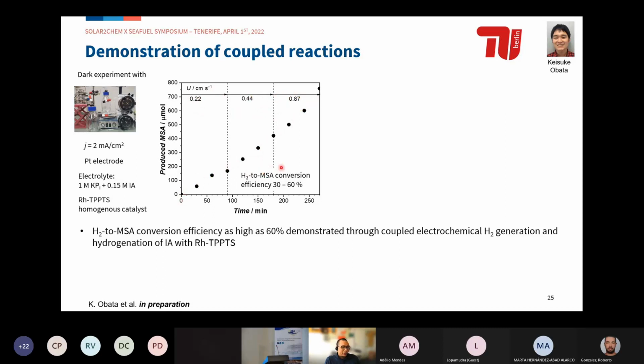The hydrogen to MSA conversion efficiency can also be quantified, i.e. how much of the hydrogen that you produce is actually used for the hydrogenation reaction. We obtained a conversion efficiency as high as 60%, demonstrating this through the coupled approach.